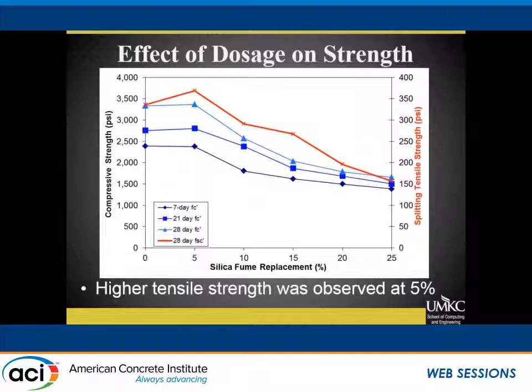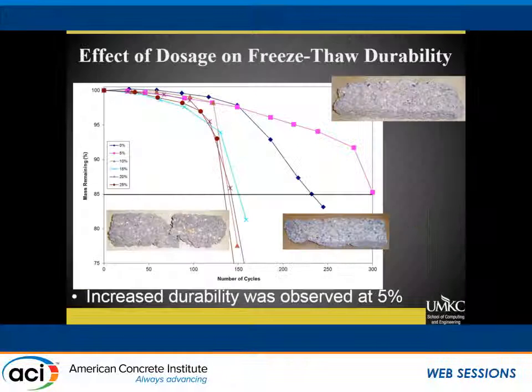We're going to look at compressive and tensile strength over time for these samples. We had kind of maintained or similar compressive strength. So 7 days we're at 2,400. 28 days we're kind of 3,400 PSI. So these are all sulfur capped samples. Compressive strength, we didn't see any increase or decrease at that 5%, but we did see an increase in splitting tensile strength, which might suggest we have a little bit better bonding happening. And then at 10% and above, because the voids crept up, our strength also fell off.